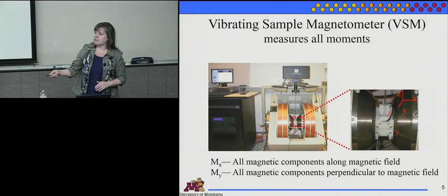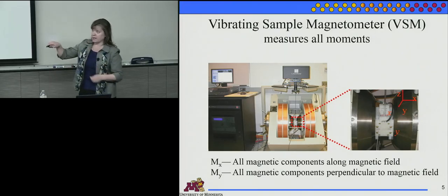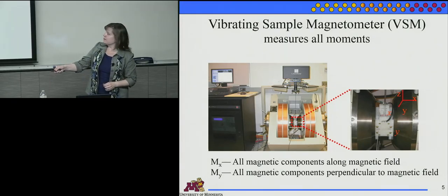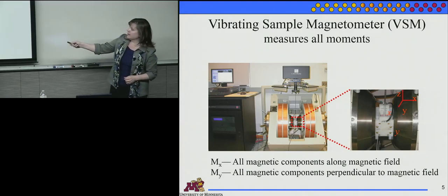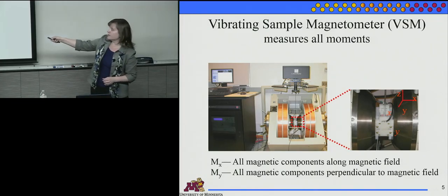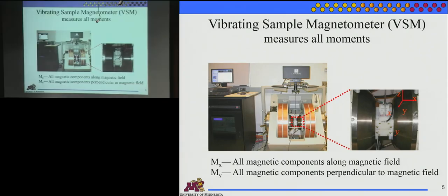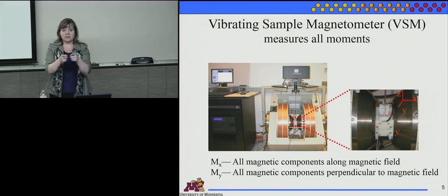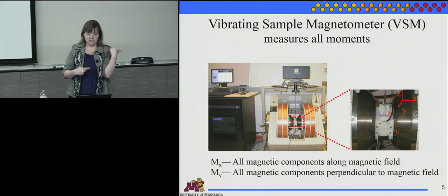Well, again, you've already seen VSM several times, but I just want to mention there's a field in this direction because these copper windings apply a field with the right-hand rule that we've talked about. But our VSM has a special feature where there's this extra Teflon, there's coils inside the Teflon here as well as here. So even though we're always applying a field in what we'll call the X direction, which would be like this or like that, we're able to pick up a magnetization perpendicular to that also. So if we see a coherent rotation as the reversal mechanism, we'll see a moment perpendicular to the applied field.